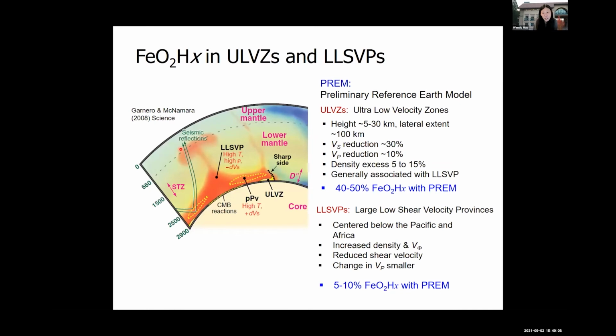So for the ultra low velocity zones, if we roughly want to match density and velocities, about 50% of this hydrogen-bearing, iron- and oxygen-rich phase mixed with average mantle would give you something consistent with ultra low velocity zones. And then maybe 5 to 10% of this material mixed with average mantle would give you something fairly consistent with LLSVPs.